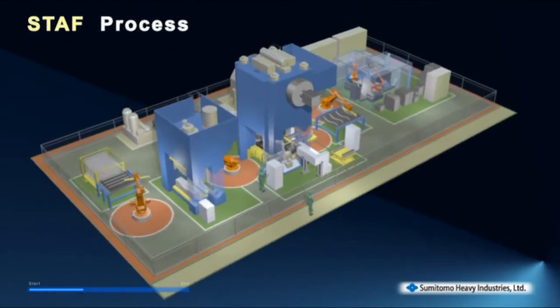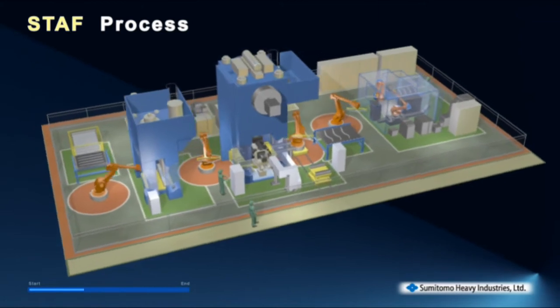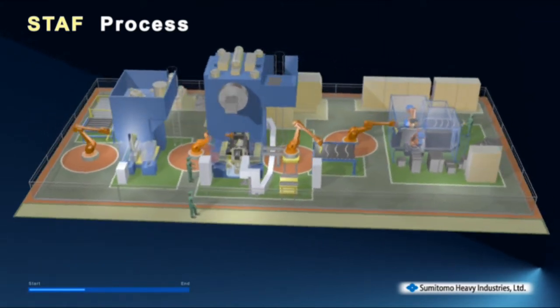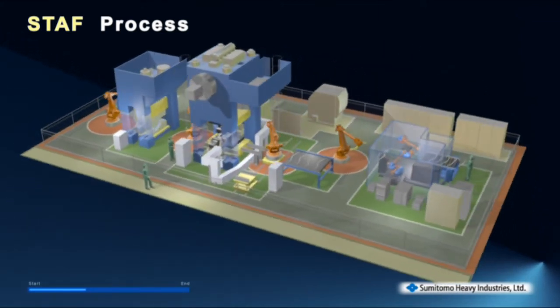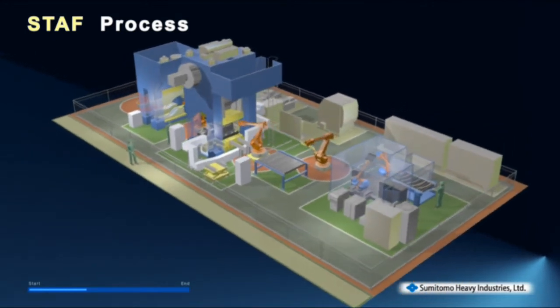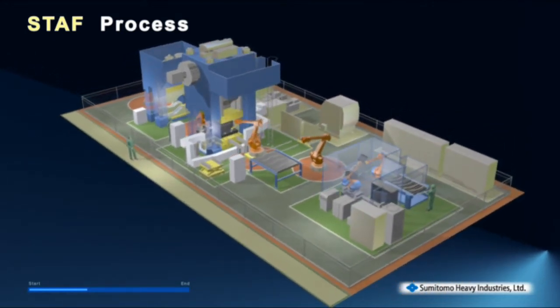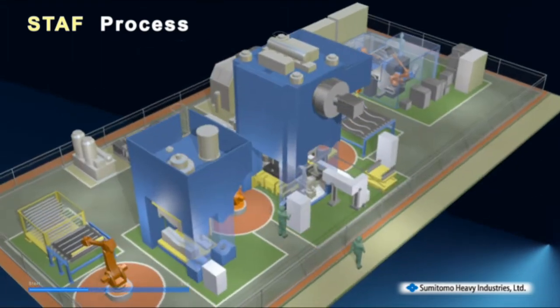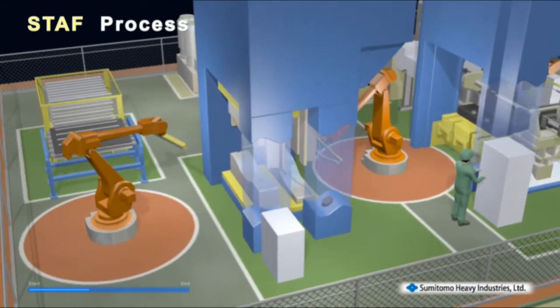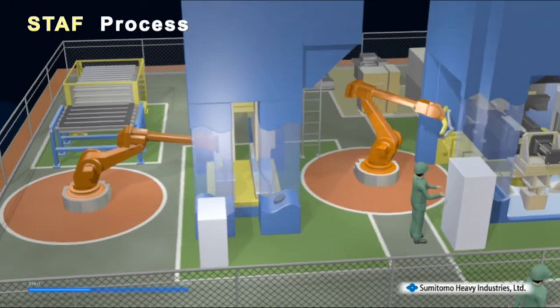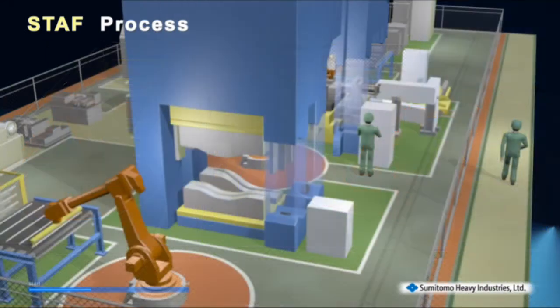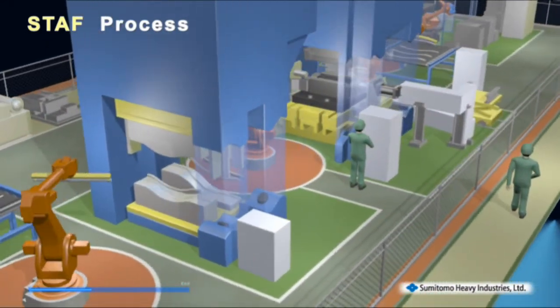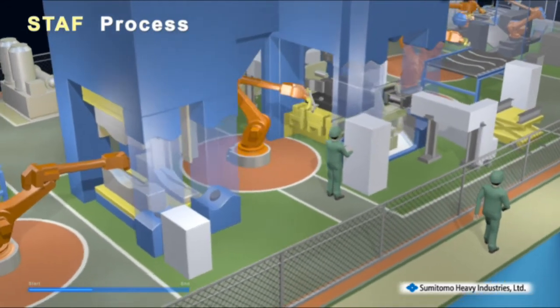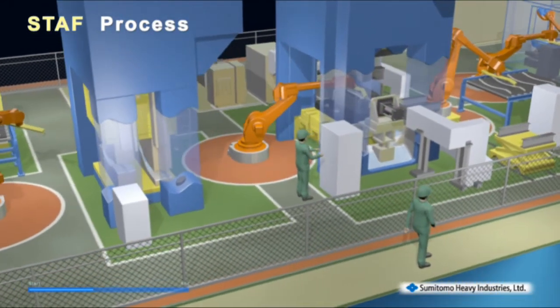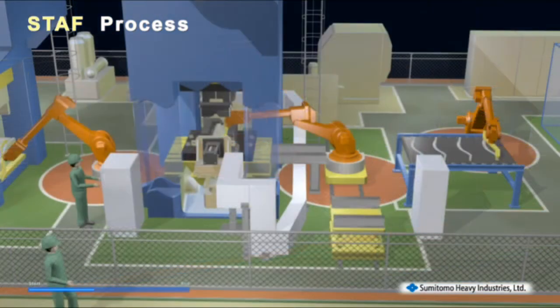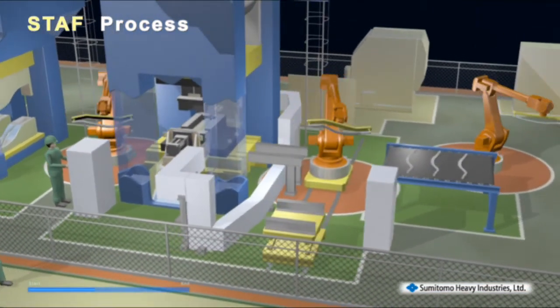Take a look at a STAF equipment line. Here is an overhead view of a line with a straight arrangement. It is 92 feet long and 46 feet wide, covering about 4,300 square feet. First, a small press does the preforming. The pipe is then heated inside the press die and simultaneously blow molded and quenched with high-pressure air. This one-step approach cools the pipe to around 200 degrees.